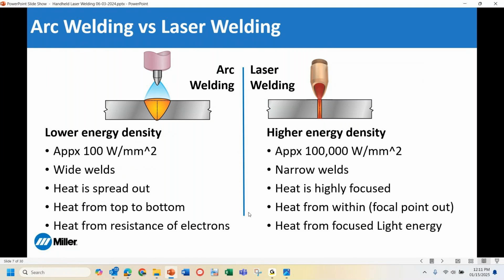So when it comes to the benefits and providing the low heat input into the component after it's welded, that all is driven by us being able to really drive power into the components at a very high rate of speed, make that weld, and not have a lot of heat soak into the surrounding material. And it also allows us to really penetrate deeply into the part, so we can avoid some of the traditional beveling processes that we had with conventional welding processes.